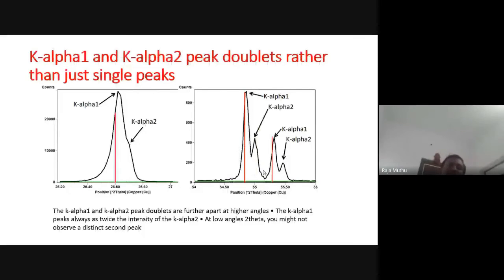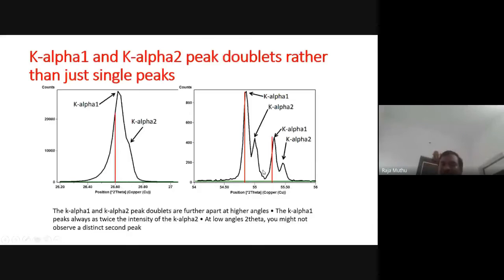K-alpha1 and K-alpha2 peaks are doublets rather than a single peak. Suppose we expect a single peak only, but because of technical issues, we will also have the K-alpha2 peak. The K-alpha2 peak is almost half of the K-alpha1 amplitude. You can see from these images, here the angle is 26 something, but here 54 and 55 something. What is the major difference in the K-alpha2 doublet? Here the K-alpha2 peak is not much visible, just a small bend, whereas here there is a gap between the main peak and the K-alpha2 peak.